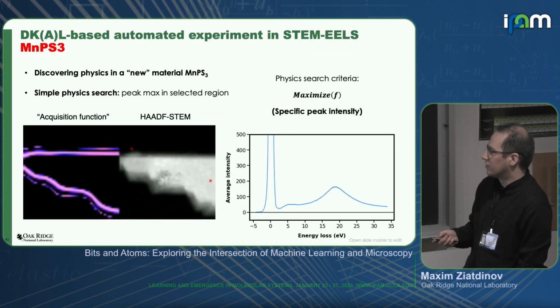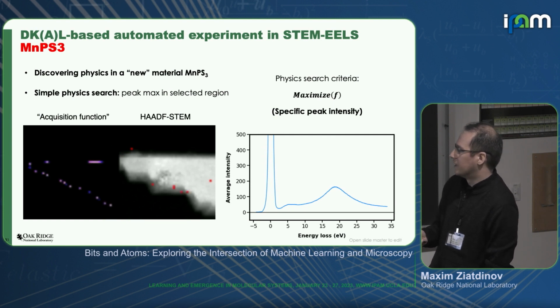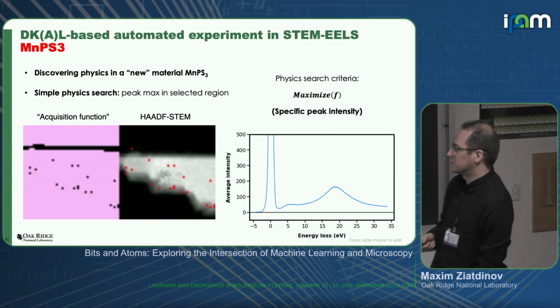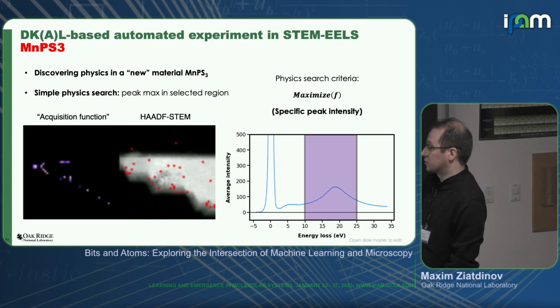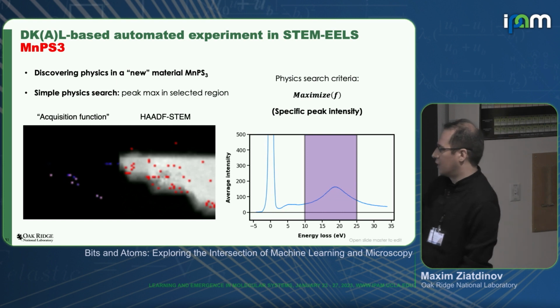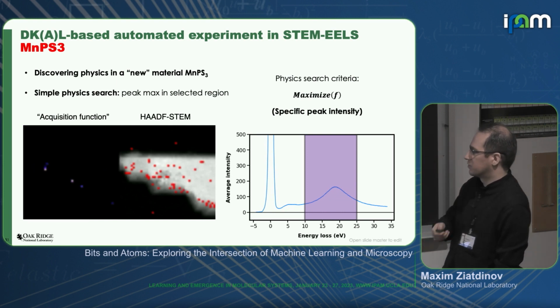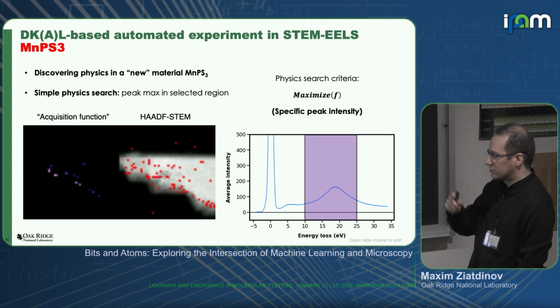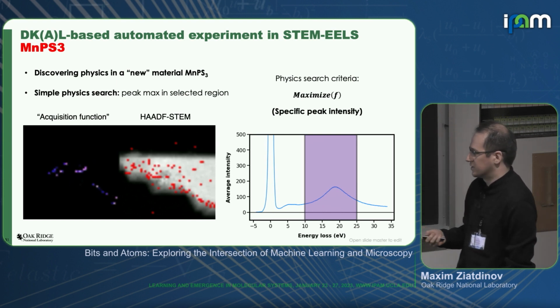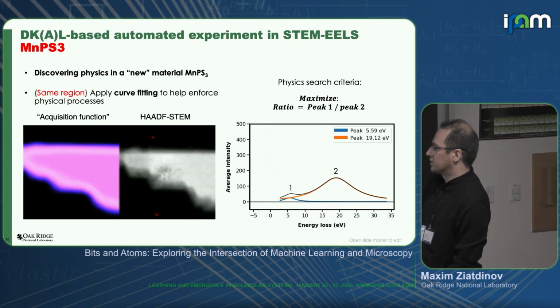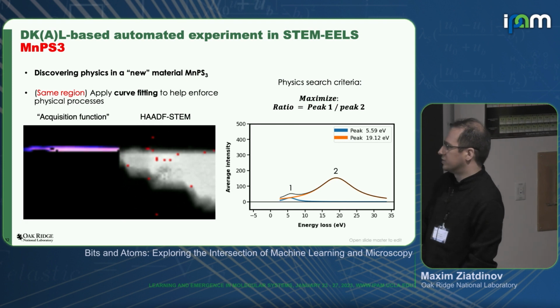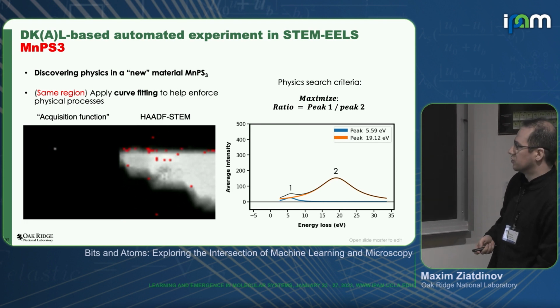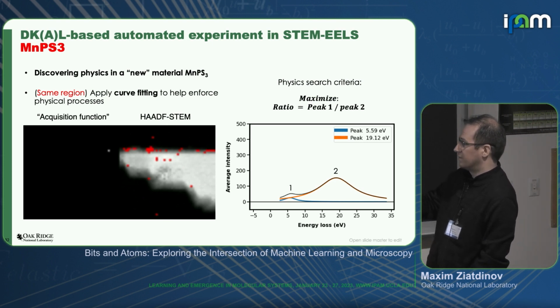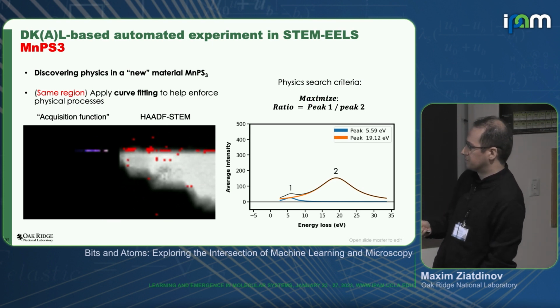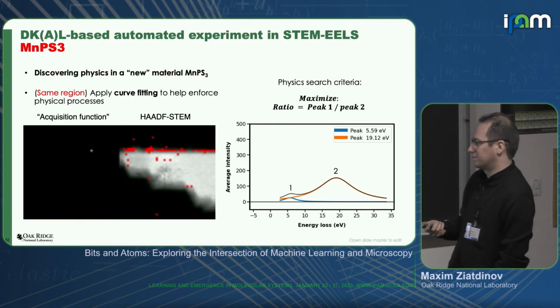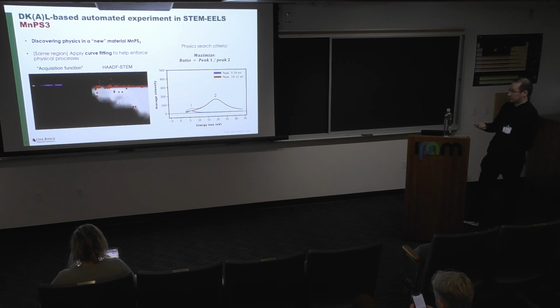Okay, and so we did it for several experiments. This was the first ever experiment where we did this. It was a proof of concept. This is all done autonomously, right? So you tell a microscope, well, I want to find all the regions where this particular plasmonic mode is maximized, go and find them. And it goes and finds them, right? And then you come back and you look at the result. And then you say, well, how about we change the search criteria and let's find all the regions of our sample where the ratio of two plasmonic modes is maximized. So this is the same field of view, and now it identifies different parts of the sample, just as we expected, right? So it looks pretty trivial, but it was the first time it ran on an actual microscope.